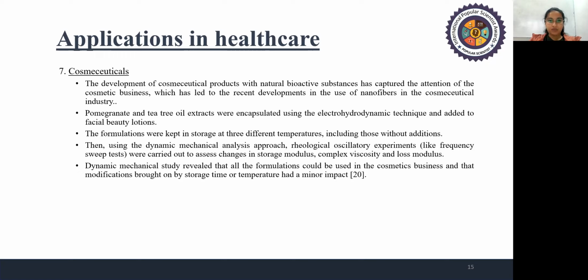Then, using the dynamic mechanical analysis approach, rheological experiments, and so on, they assessed the changes in storage modulus, complex viscosity, and loss modulus. The dynamic mechanical study revealed that all formulations could be used in the cosmetic business, and that modifications brought on by storage time and temperature had minor impact.